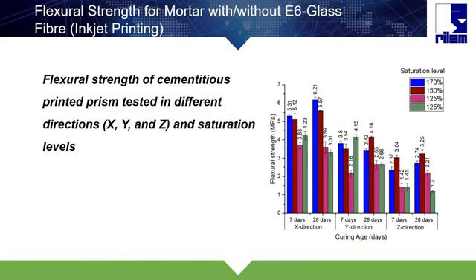As we can see here, it shows the flexural strength for the mortar with or without E6 glass fiber for inkjet printed specimens, and it clearly shows that materials with different saturation and different direction show different results. That obviously shows at 28 days that we get very good flexural strength results with the highest saturation level. Here we mean the saturation level as the water cement ratio. Basically for that water cement ratio we got about 0.52, which equals 170% of the saturation level. We get good results at that point.